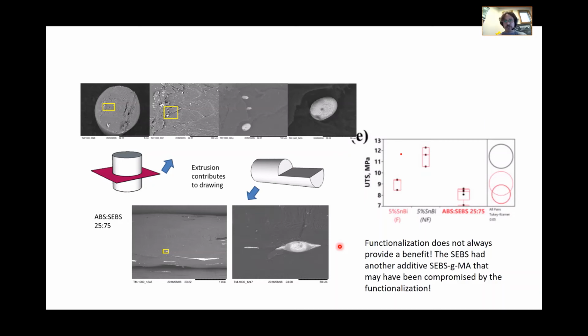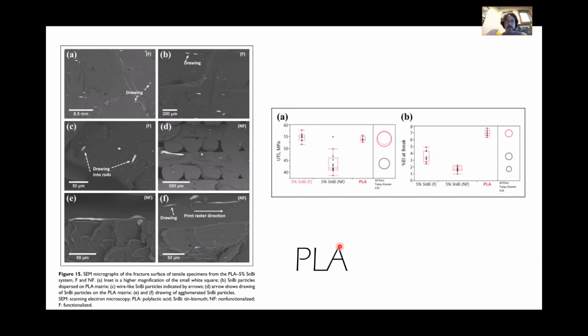PLA was interesting because it didn't actually show a big strength increase. In fact, the non-functionalized did not show any strength, it was actually detrimental, and the functionalization barely gave a little bit of a kick. It did compromise the flexibility of PLA, so we actually lowered the percent elongation - we made it stiffer. So we maintained the strength, made it stiffer, which may actually be good in other applications.